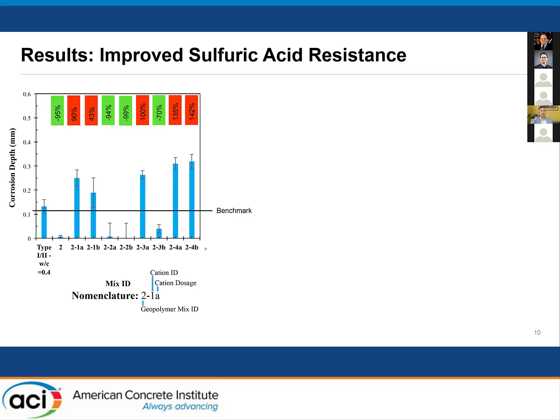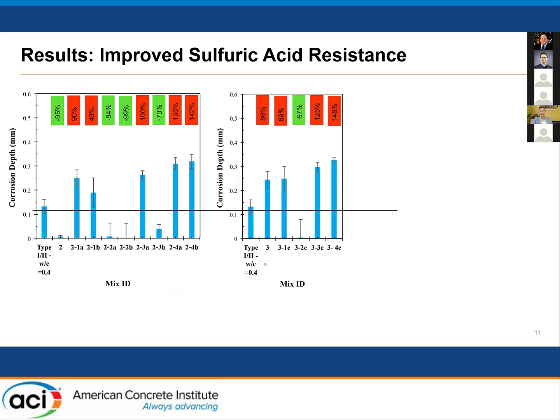And you can see from these results that some of the cations worsened the performance, and we have theories as to why, but you can also see that cation number 2 improved the performance even at low and middle concentrations. So it exhibited on average an improvement compared to the original formulation. We didn't test all cations at all dosages because we used a design of experiments to minimize the total number of samples. But we did test cation additions to mix number 3.